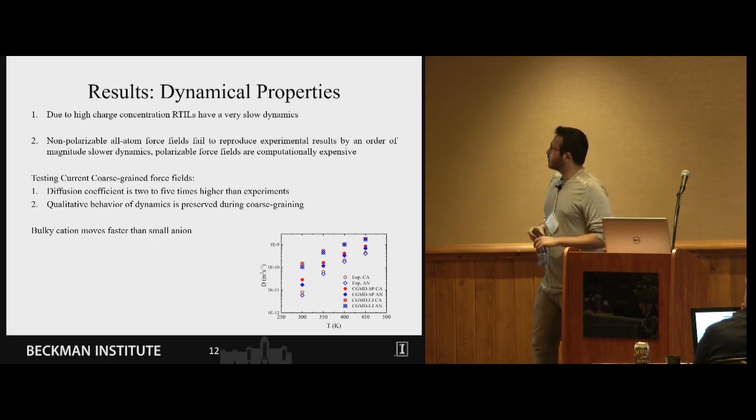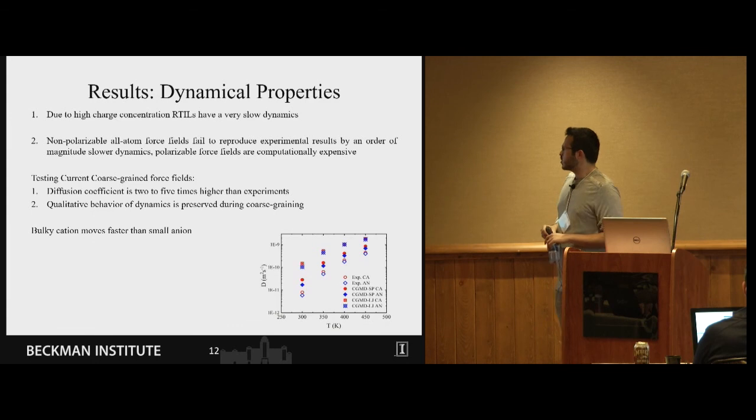We wanted to see how our force fields work because it is a force field designed to reduce the computational cost and to work for different systems and it should be transferable. So we calculated the diffusion. It was two to five times higher than experimental value but the important property that we were looking for was to see whether qualitative behavior of dynamics is preserved during the coarse graining or not.